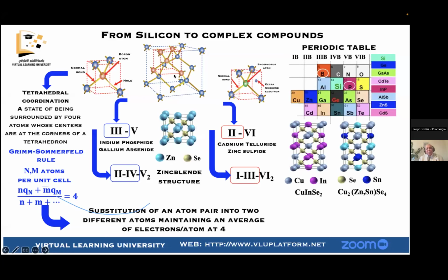I just show you this because it's the topic on which I worked at least 20 years, where you can see that the symmetry of silicon, when you go from silicon to the quaternary compound, is changing. But the valence stays during the substitution from silicon to binary compound to ternary compound, either in this direction here or with II-VI to I-III-VI2. You have the same number of electrons, the neighbor of one element here. So this is very interesting.